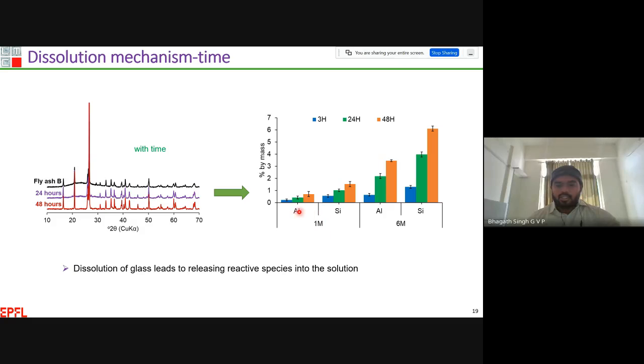At 1 molar, you can clearly see from 3 to 48 hours a clear increase in the alumina element concentration in the solution. Whereas at 6 molar, you can see a significant improvement in the dissolution of alumina ions from 3 to 48 hours, and likewise from 3 to 48 hours in the case of silica. By the end of 48 hours, most of the amorphous glassy phase of the fly ash is dissolved, which means that alumina and silica species came into the solution. What I'm trying to say is that dissolution of fly ash glass leads to the release of reactive species such as silica and alumina into the solution, along with other elements.